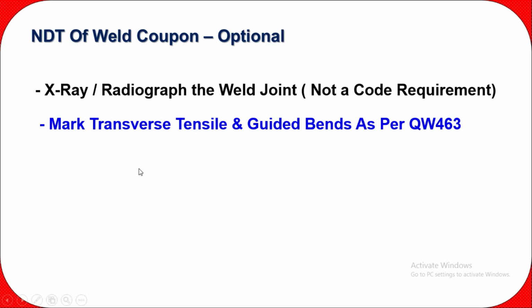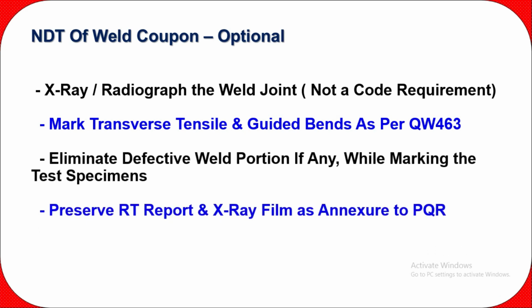Mark transverse tensile and guided bend as per QW463. This is the requirement in ASME Section 9 QW463. You have to mark the transverse tensile and the guided bend test specimens. Eliminate defective weld portion if any while marking the test specimen. If you find some defective area in the weld test area of the full plate, you have to remove it while marking the test specimen.